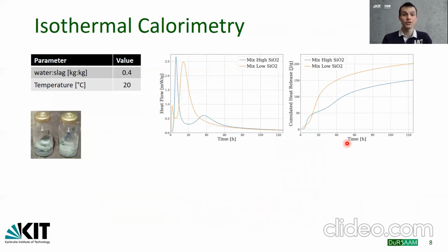And as I said, to understand and model strength development and shrinkage of alkali-activated slag, one should look at the reaction kinetics and predict the degree of reaction. And to do so, one can use, for example, isothermal calorimetry experiments on a paste level. The pastes were prepared outside of the calorimeter, mixed and homogenized, and put in less than 5 minutes in the calorimeter chamber.